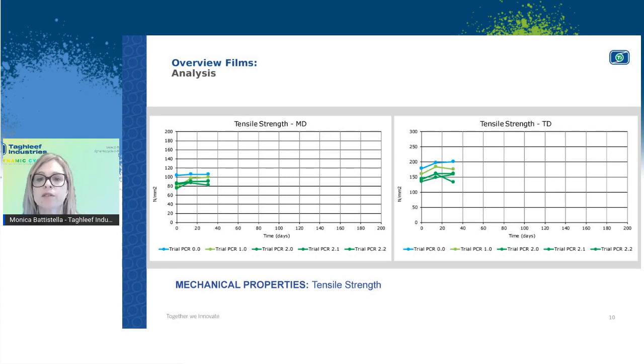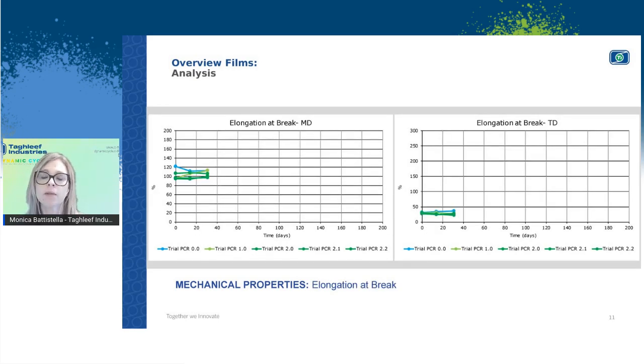In this case, we had different samples. Starting from the zero sample, which is the reference one, up to the 2.2 samples, we see the performance in tensile strength, both in machine direction and transversal direction. And we do not see significant discrepancies which would let us think that the films with a mechanical recycled content would not be usable for the application. The same goes for the measurement of the elongation at break, both in machine direction and transversal direction. You see, especially here, the lines are basically one next to the other.